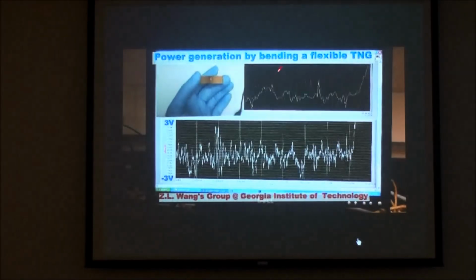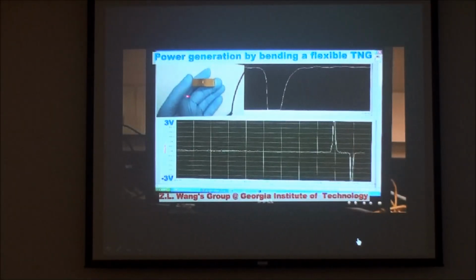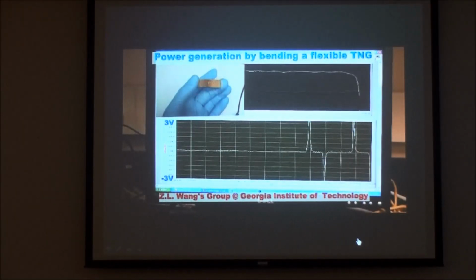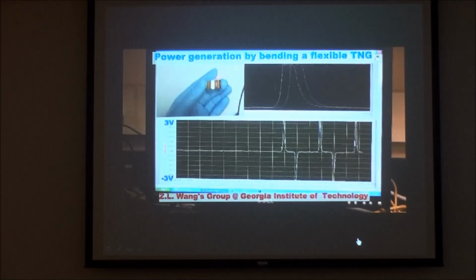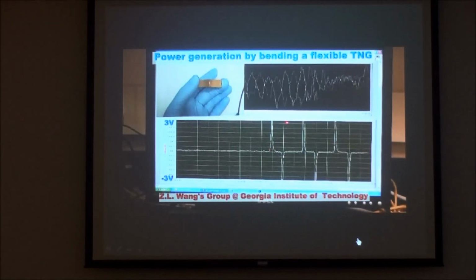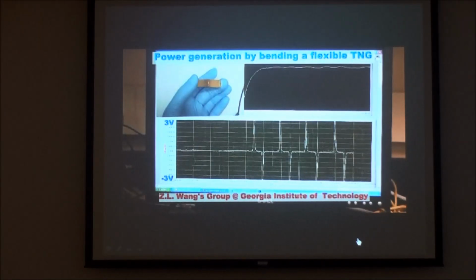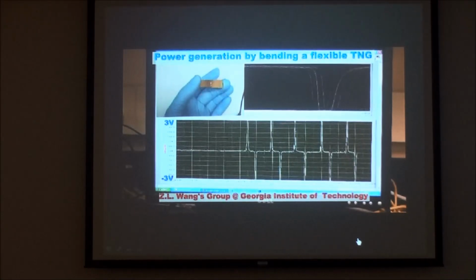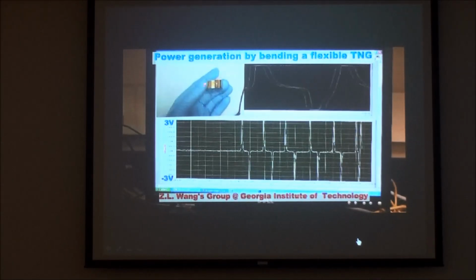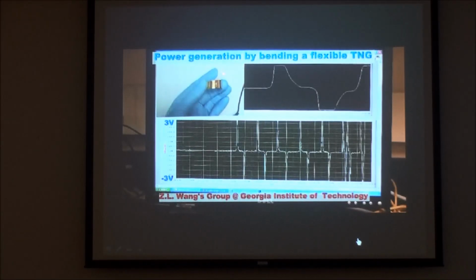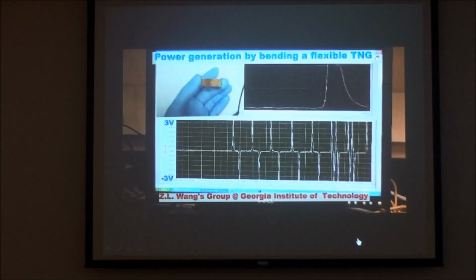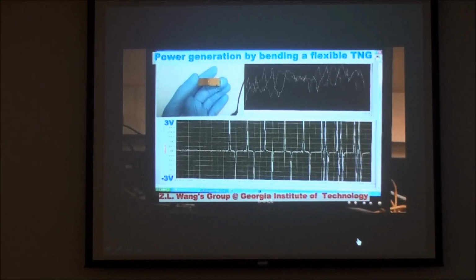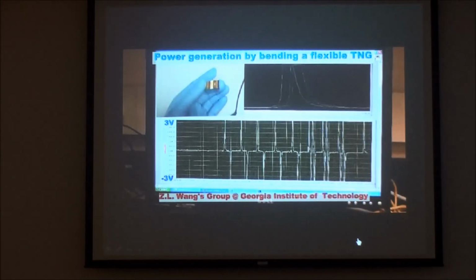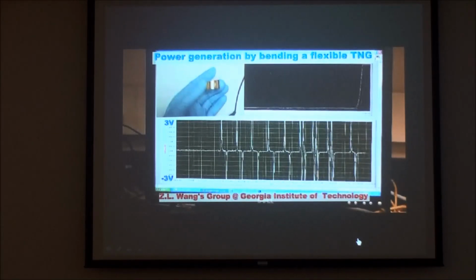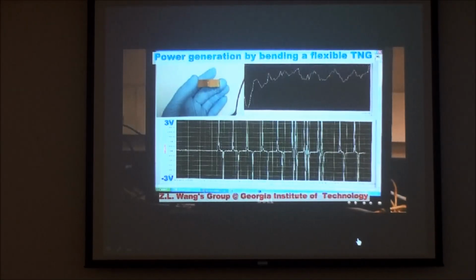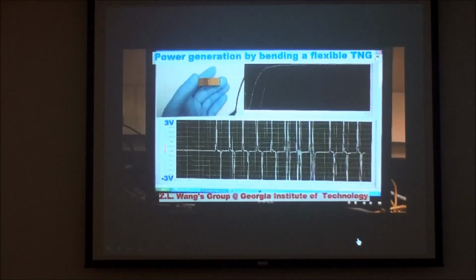Okay. First, look at this one. These are 2 pieces of polymer with some nanostructure introduced on the surface. You see the electrode here. When you mechanically deform this, we get a voltage, a few volts of output. There is no piezoelectric material here, just relative sliding of one polymer against the other. What we used to know is that the triboelectric effect gives you charge. But how can this charge produce a potential to drive the electron to flow? That's the current, that's the power output.